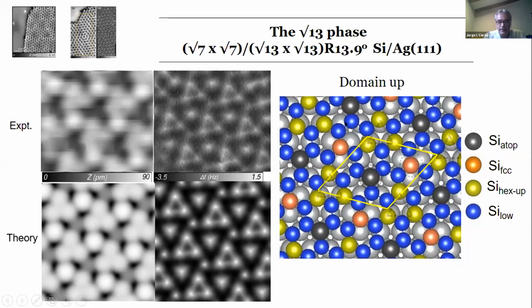Okay, as I see, we can identify immediately all the features here. We have that the triangles are always related to hexamers. The brightest bump, this one here, is related to the highest lying silicon atom, and the dimmer bump, this one here, is related to the silicon sitting on the FCC site. Okay, but what about the other domain?